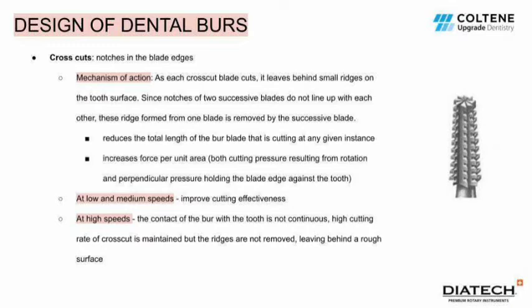The next parameter that we'll discuss is cross cuts, which are only present in certain burrs. These are notches in the edges of the blade. The mechanism of action is that as each cross cut blade cuts, it leaves behind small ridges on the tooth surface. Since notches of two successive blades do not line up with each other, the ridge formed by one blade is removed by the successive blade.